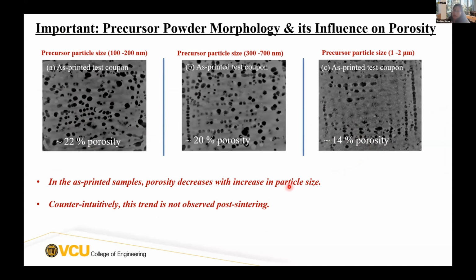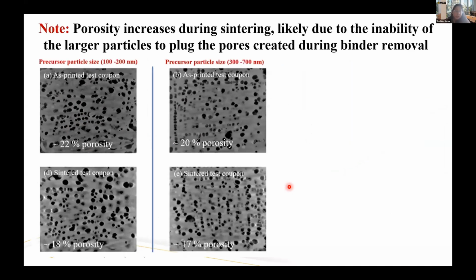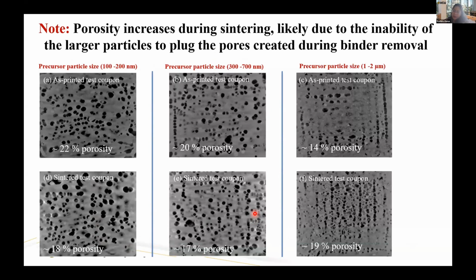Counterintuitively, surprisingly, we noticed this is not observed post-sintering. When the particles are small, after sintering, we see a reduction in porosity, going from 22% to around 18%. But when the particles are big, microns in size, after sintering we see an increase in porosity, which was surprising. We realized this is likely due to the inability of the larger particles to plug the pores created by binder removal.